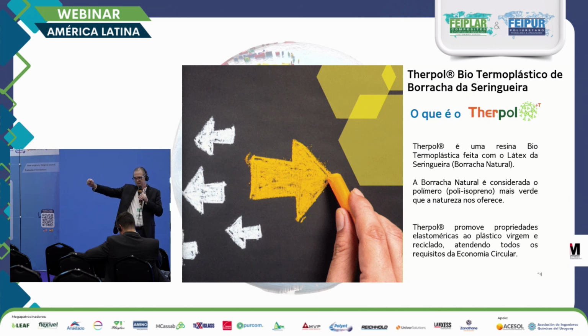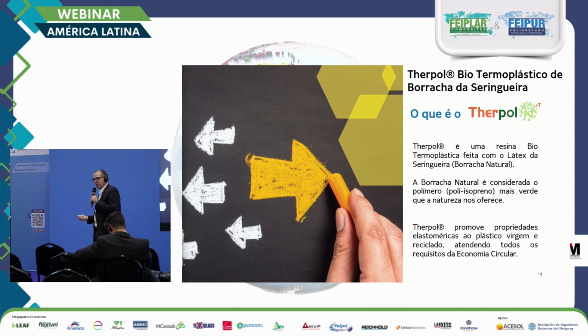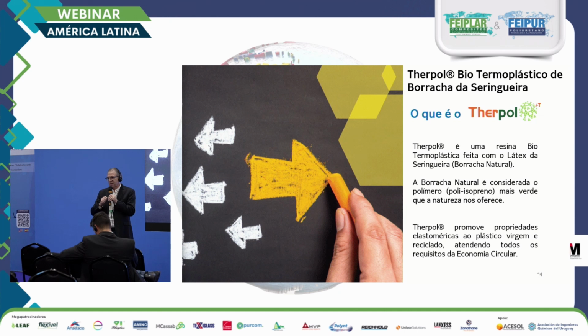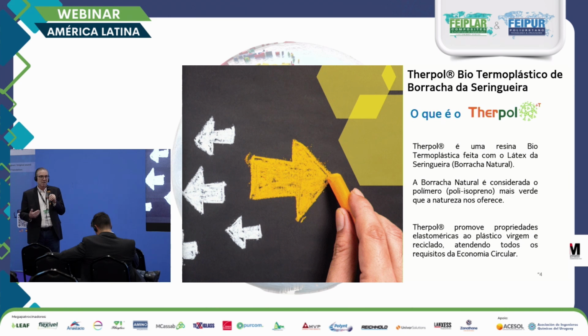So when we transform a rubber from a gum to an elastic by adding sulfur or peroxide at high temperature, that's a cure process. And it goes from being a gum, and with temperature or sulfur or peroxide, it'll turn into an elastic and it won't go back again. A tire, you can grind it, use it as a charge somewhere, but most of them are burned because there's no recyclability, and that's one of the biggest challenges in the automotive industry, because after you vulcanize it, it won't go back.